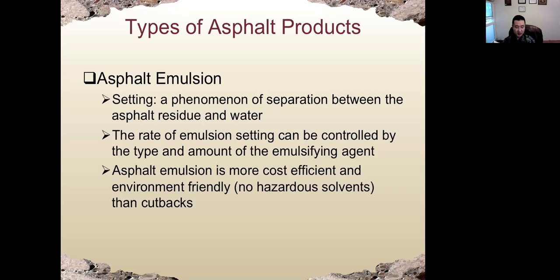So for asphalt emulsion, the setting, which is how soon the asphalt will harden, is the phenomenon of separation between the asphalt residue and the water. In the water we have a small percentage of emulsifier agent, and the rate of setting is controlled by the type and amount of this emulsifier agent. It is more cost effective because mostly we have water and only a small percentage is emulsifier agent. It's also more environmentally friendly because not a lot of solvent is used, unlike in the second type.